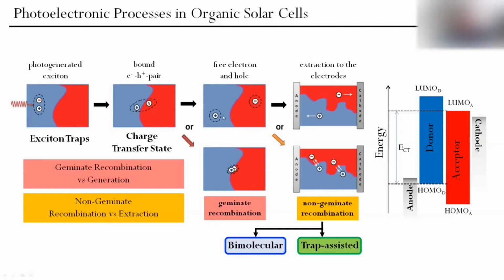So this is one mechanism of recombination. There is another. Even if they are split and already move towards electrode, they can recombine on their way. And it's called non-geminate recombination, when electrons and holes from different excitons, or after the separation at the interface, can still meet each other and recombine in this active layer. So we get different types of non-geminate recombination. It can be bimolecular, when we have direct contact of electron and hole in the active layer. They meet each other within some cross-section area and recombine. It can also be called band-to-band recombination, recombination of electron from the conduction band and hole from the valence band.